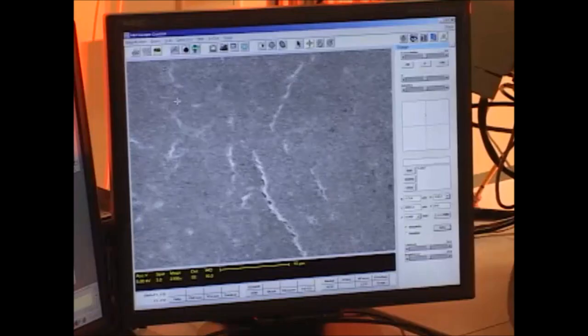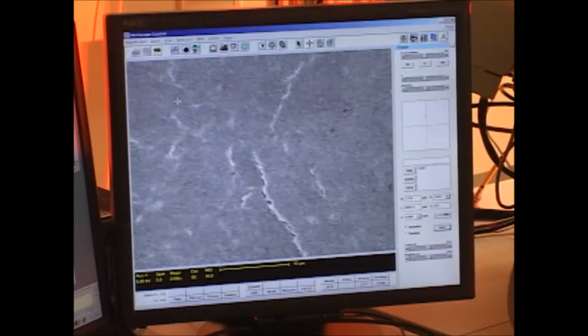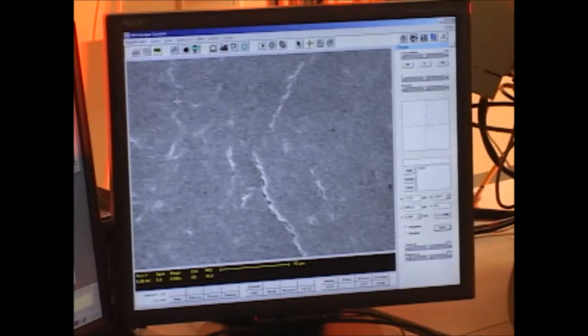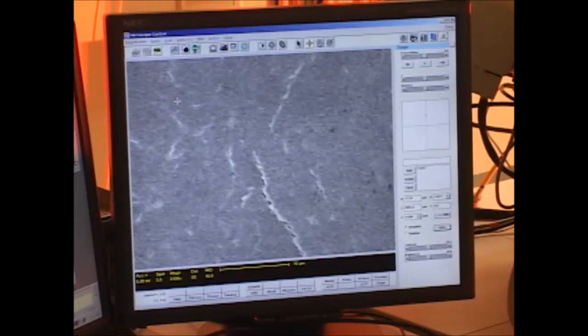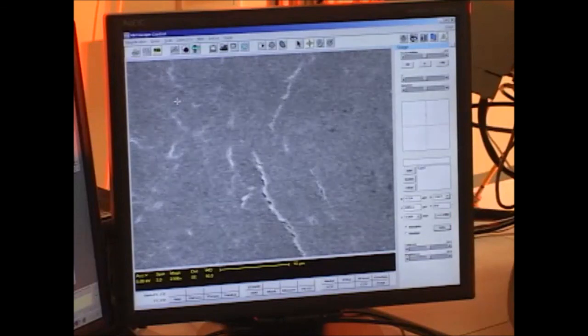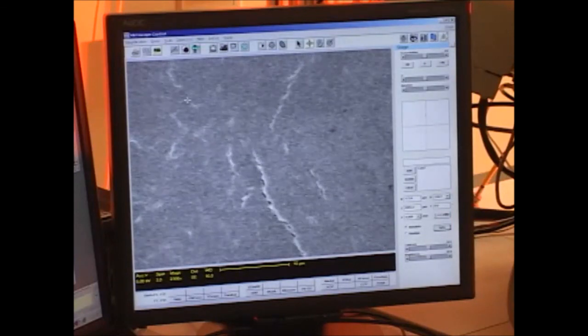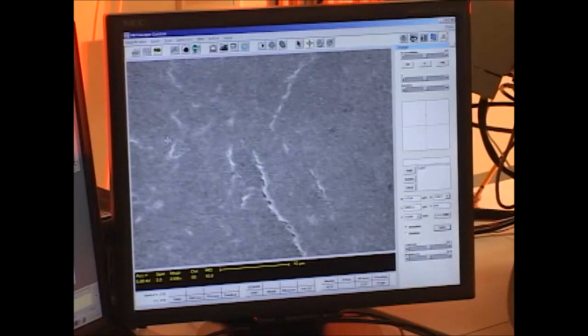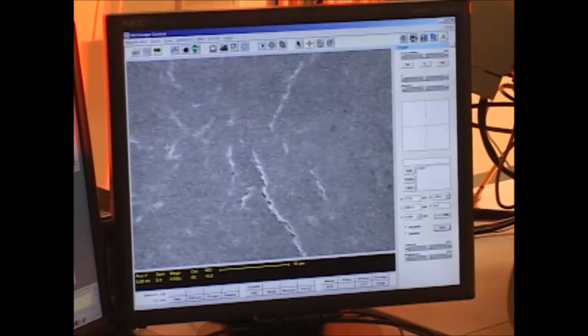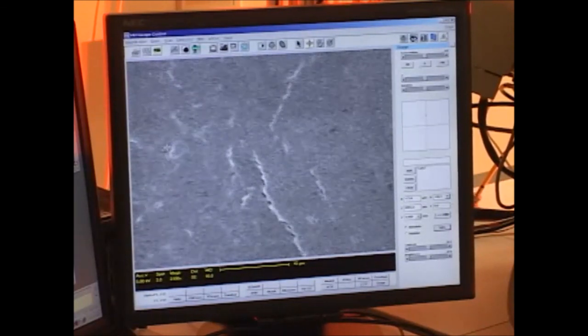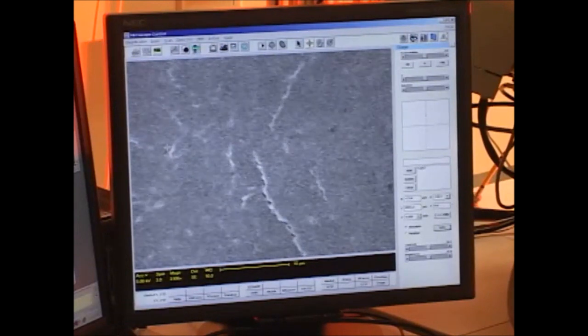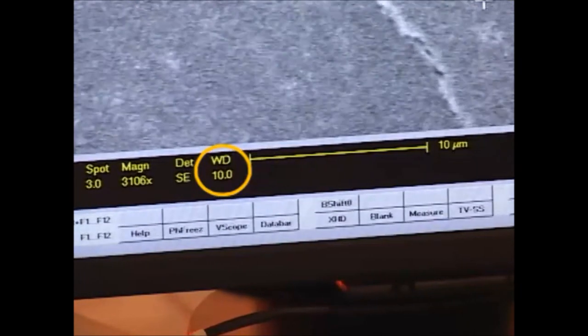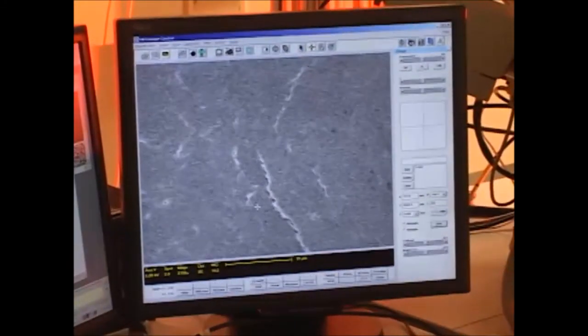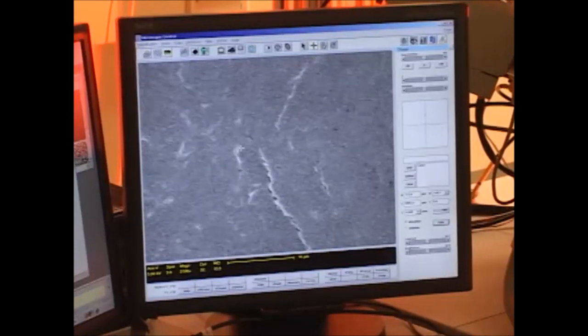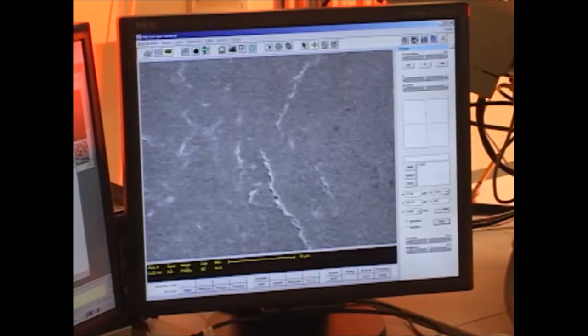the detector. If you're careful about following the protocol and the sample is in focus before you move it, you shouldn't need to cancel the vertical movement. But in case there's a problem, you accidentally focus on the wrong part of the sample, for example, you want to be ready to stop that vertical movement before any damage is done to the machine. So my working distance now is 10 millimeters, and the resolution of the stage motor is on the order of microns, so it doesn't go to exactly the position that I want it to go to.